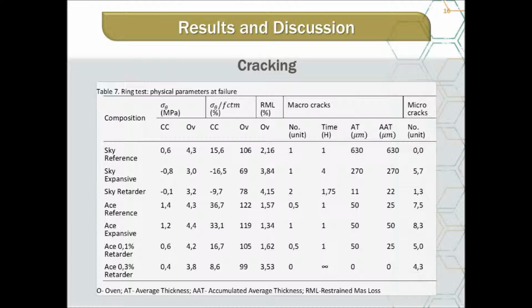Cracking. By analyzing the ACE mixes, it can be seen that the shrinkage strain, the tensile stress, and the stress-strain ratio decrease with the setting time. This behavior can be explained by a larger expansive period developed due to higher setting time. Consequently, the higher setting time reduces the number of cracks and the crack area.